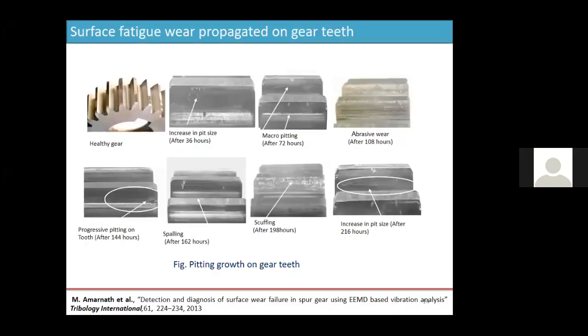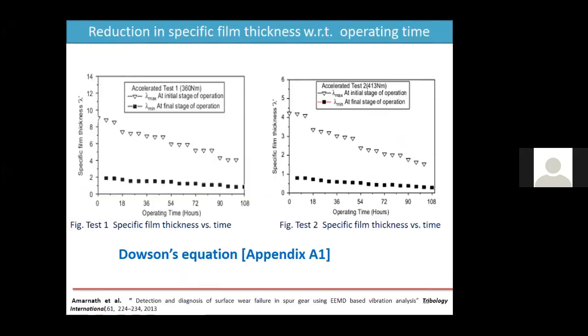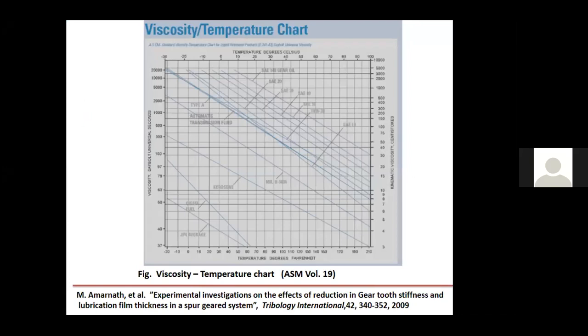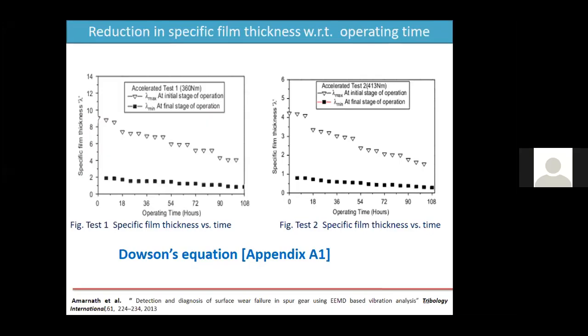Then, in addition to this, you can also consider wear particle analysis. I'm explaining these parameters because all of them will be considered for nano lubricants to get the details of nano lubricant performance. All these parameters should show a reduction if you use nano lubricants. That is the objective of discussing these lubrication aspects of machine elements. For example, specific film thickness is estimated using ordinary SAE oil. If you use nanoparticle based SAE oil, then the specific film thickness should go up. There will be enhancement in lubrication regimes. That is the purpose of discussing the lubrication analysis of gears.